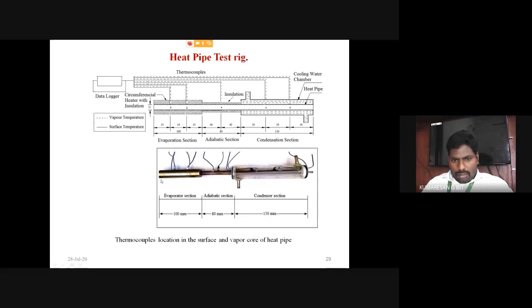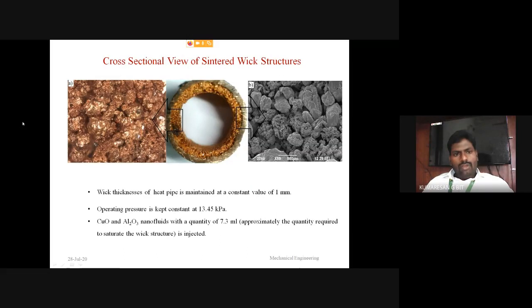Okay, so this is the fabricated heat pipe: the evaporator, adiabatic, and condenser sections, and these are the thermocouples. You see here, there are two thermocouples attached at a particular location to measure the surface as well as the vapor temperature value. Okay, so this is the cross-sectional view of the sintered wick structure. This is an SEM image of the sintered wicks, and the wick thickness of the heat pipe is maintained at a constant value of 1 mm irrespective of the wick structure. Even for the mesh, sintered, or the combination of mesh and sintered wick structure, the wick thickness is maintained constant at 1 mm.